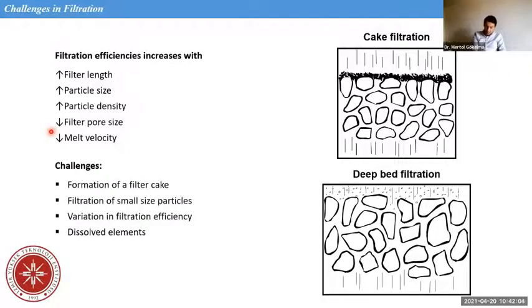So the challenges in filtration are, first, the formation of a filter cake. Sometimes it is wanted to have a bit of filter cake, but not much, because it decreases the life of the filter, so you have to change it because it clogs. Another challenge is filtration of small size particles. Small size particles can easily go through the filter, and then in the melt, when they agglomerate after filtration, they become a big cluster again and make problems, such as aluminum carbide particles.